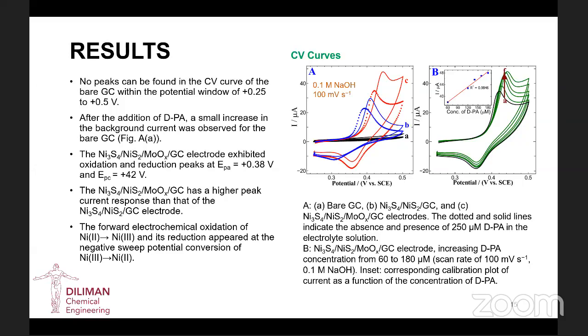So when DPA was added into the solution, the modified electrodes exhibited oxidation and reduction peaks at 0.38 volts and 0.42 volts. Okay, so the material with molybdenum oxide has a higher peak current response than that of the material without molybdenum oxide. And based on these CV curves, we propose a mechanism wherein the forward electrochemical oxidation of nickel 2+ to nickel 3+,